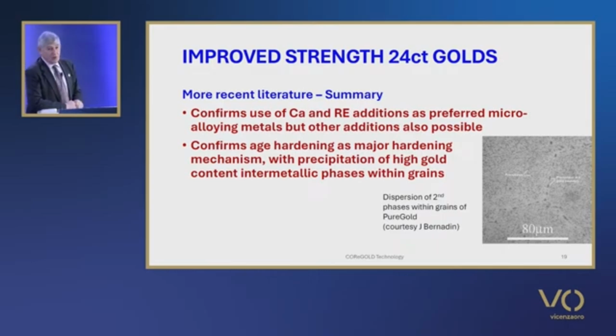So I think in summary from all of that, we can say that the more recent literature confirms the use of calcium and rare earth additions as preferred microalloying metals, but other additions are also possible. It confirms age hardening as the major hardening mechanism with the precipitation of high gold content intermetallic phases within the grains. And in the picture, it's a microstructure of the 3O company's pure gold, and we can see there are some precipitates on grain boundaries, but the whole of the internal grains has got a very fine distribution of the intermetallic hardening phase.